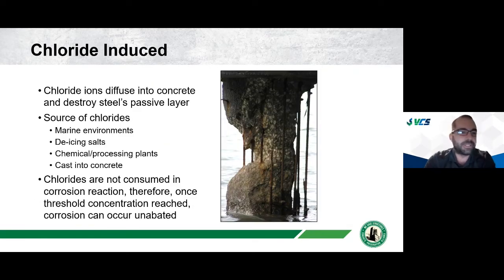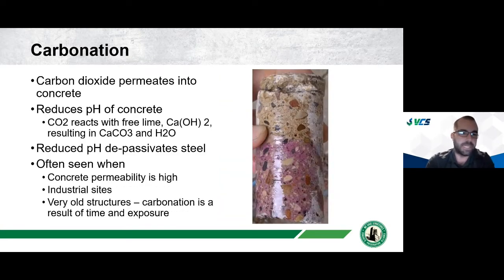So obviously with marine structures, chlorides are going to be our significant factor with regards to corrosion activity. Chlorides are typically going to be the cause of our damage. Chlorides get into the concrete matrix and break the passivity of the steel and cause corrosion. Now, corrosion can also be caused by carbon dioxide in the air permeating into concrete and lowering the pH. But in a marine environment, due to the moisture and chloride exposure, this is less common of a concern because chlorides move typically much faster than carbonation.